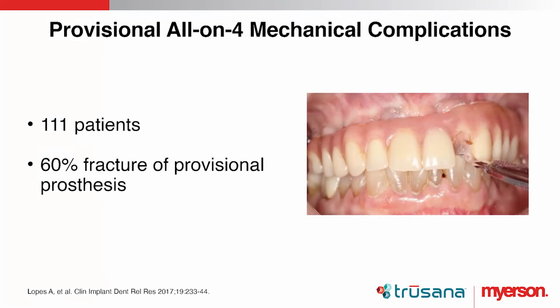And then lastly, probably the biggest offender was the provisional of the all-on-4, which was the prosthesis that we put in immediately after placing the implants during this period where we're wanting to have a stable integration period, right? And then find out that 60% of them are fracturing. And you know that also can jeopardize the integration.